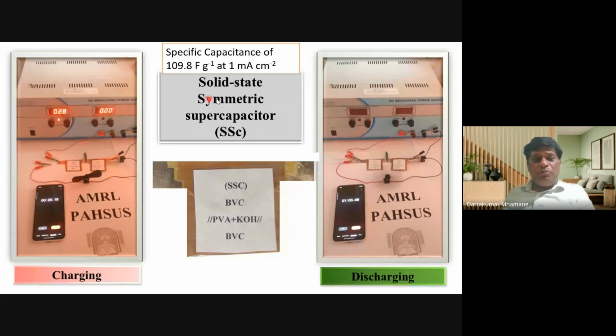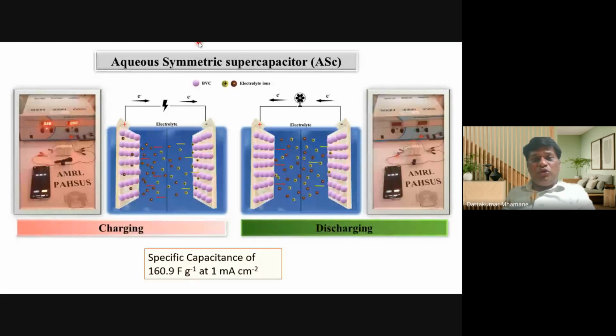This is a symmetric supercapacitor in our laboratory. I will show you the video. This is charging going on. Okay, and this is discharging at right side. And then we also prepared an aqueous based supercapacitor. This is charging at left side. This is discharging, and we got 160 farad per gram capacity. The important point is that we use around 20 milligram of active material, and that is why the capacitance is a bit low, but the device is very good.